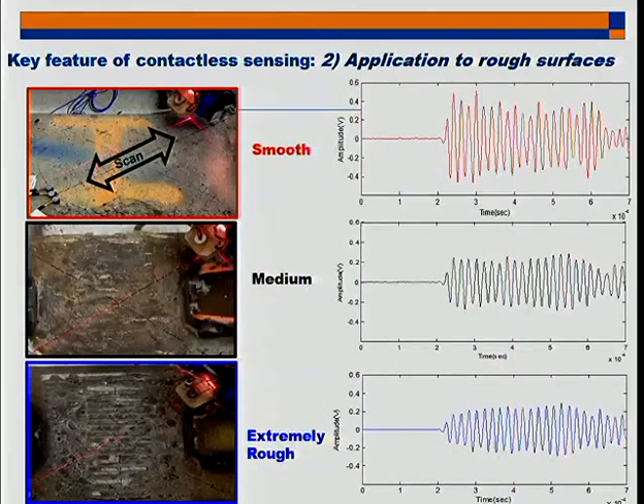Another benefit of air coupling is that it's insensitive to the surface condition. If any of you have ever done tests where you have to mount things onto concrete, strain gauge or some sort of sensor, you know that the surface condition of the concrete is critical. And in real life, not all concrete is smooth and polished and clean. It's dirty, rough, and cracked. And in those cases, it's very hard to attach a surface-mounted sensor. In some cases, you can't. It's just too far gone unless you grind it down. So that's another energy and time investment that is not helpful.